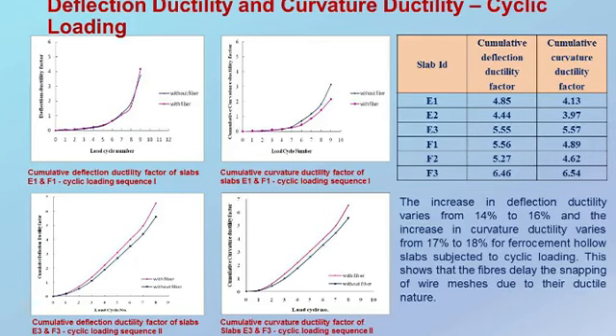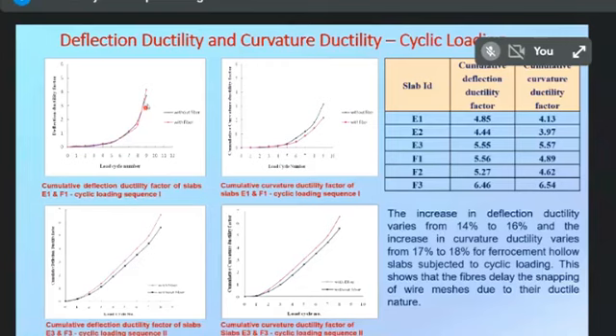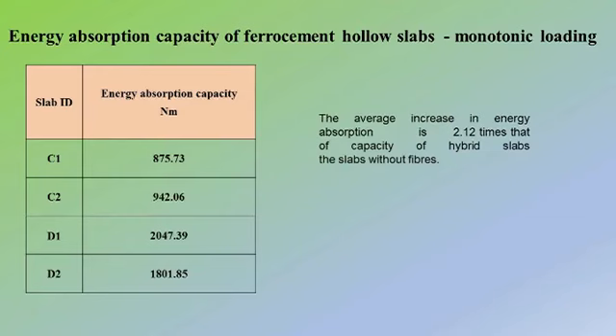So this is for cyclic loading. For every load cycle, the deflection ductility factor was taken and a graph was plotted. Here the blue indicates without fiber, and the pink one is with fiber. It is seen that the increase in deflection ductility varies from 14 to 16%, and the increase in curvature ductility varies from 17 to 18% for the ferrocement hollow slab subjected to cyclic loading. So this shows that the fibers delay the snapping of wire meshes due to their ductile nature.